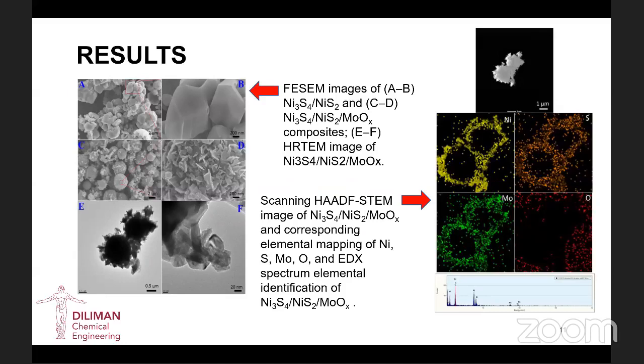So for the results, you can see here the FESEM images of the composite with and without molybdenum oxide. So A and B are for the Ni3S4/NiS2 composite. C and D images are for the composite with molybdenum oxide, whereas E and F are the HRTEM images of the molybdenum oxide composite. So we can see that images A and B show irregular bulk particles with size ranging from 1.5 to